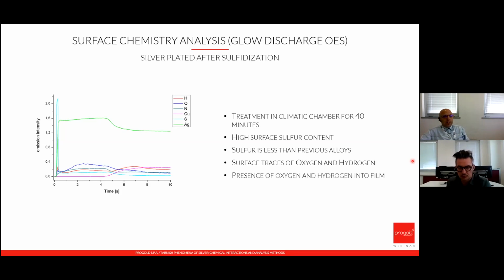The direct sulfidization in the climatic box for silver-plated sterling surprisingly gave a lower sulfur concentration than the ultraviolet test, though relatively high, revealing anyhow the protecting action of the anti-tarnish additive in the galvanic coating. Here, from the xenotest, the values were about twice, for example.